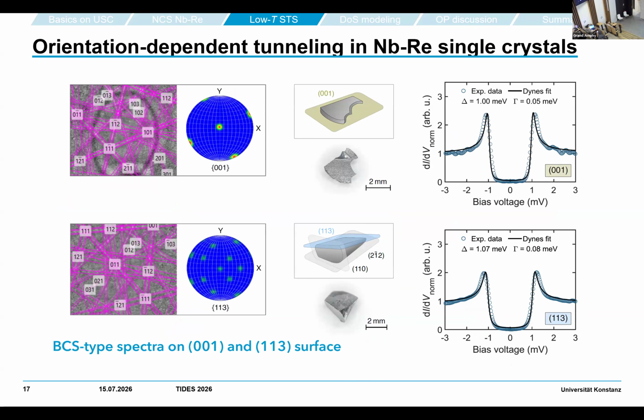So let me start with the two boring planes. These are the 001 and the 113, measured by EBSD, so that these are really these planes. And what we do see there is basically fully gapped BCS that can again be described with a Dynes parameter, typical gap size a millivolt, which corresponds to the TC, which is 8 point something Kelvin in our case.